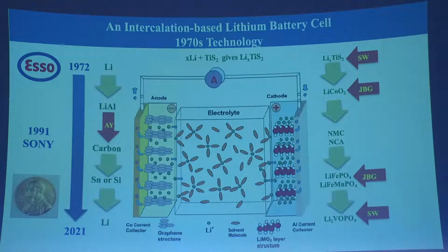So we looked at lithium. We saw dendrites early on, so we switched to a lithium aluminum alloy. If you do any semiconductor work, you'll know the semiconductor people will tell you we don't want lithium anywhere near our chips. Lithium reacts with everything. So lithium will react with aluminum at room temperature with no problem at all, forming the one-to-one alloy. So we worked with that material and used it in most of our commercial batteries for safety. It's good for 10, 20 cycles, but it crumbles very quickly.